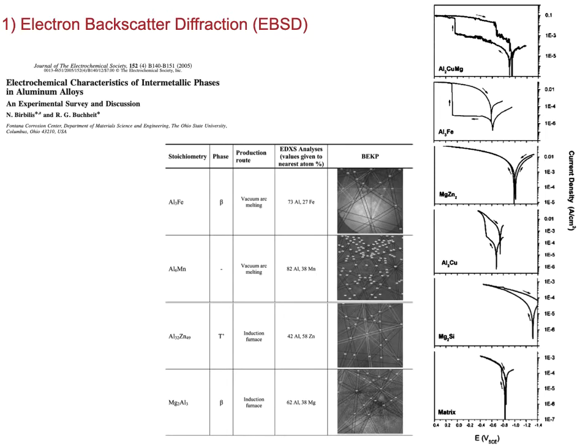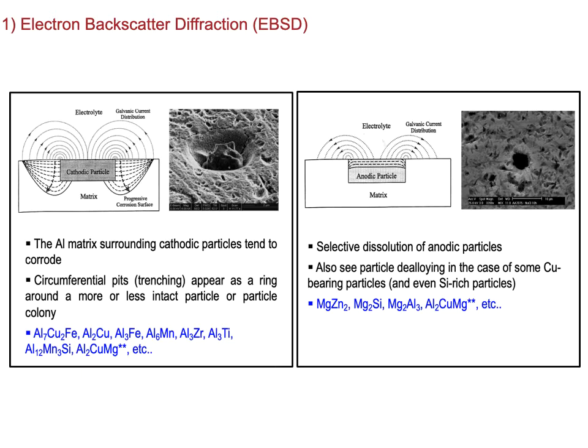So by being able to use EBSD to do surface phase ID in a way that can't be done with X-ray diffraction, the electrochemical microcell allowed us to unravel the behavior of nearly all intermetallics in aluminium alloys to date, and an example is shown here on the right for a number of the key intermetallics that populate 7075. So first order determinism allows an electrochemical classification of the role of microstructural features and their subsequent influence on corrosion morphology.